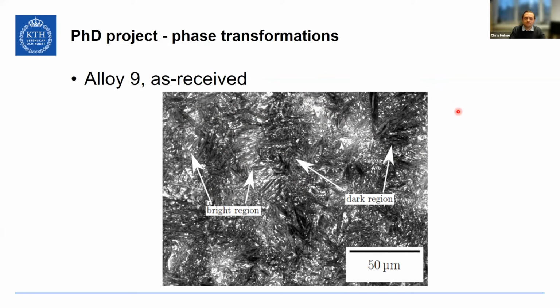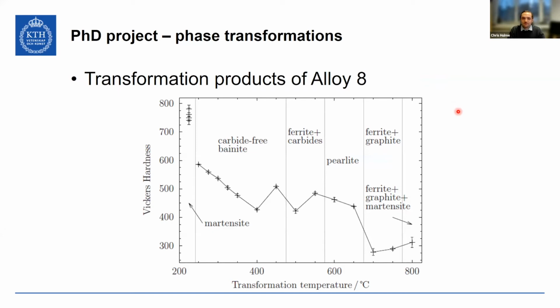Another thing which I was very, very happy with was that alloy 8 behaved extremely well for a steel alloy. Just transforming it at different isothermal transformation temperatures gave very different hardnesses and very different phases. So at 800 degrees, we formed extensive graphite nodules, followed by ferrite, and large grains of ferrite and martensite in between. A bit cooler, you go from a three-phase mixture according to the thermodynamics to a two-phase mixture of ferrite and graphite. That's exactly what we formed. At lower temperatures, we formed pearlite. Below that, ferrite with islands of different carbide, including cementite. And then below 450 degrees, we formed carbide-free bainite.